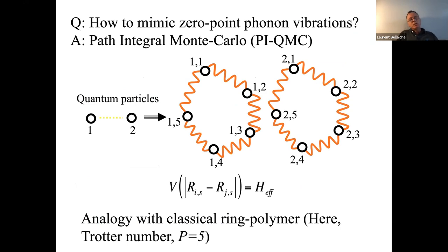Imagine you have interaction between two particles on the quantum level, particle one and particle two. Quantum effects means that particle one self-interacts with itself via a classical ring polymer. And this is denoted as the Trotter number. So if it interacts five times with itself, it means your Trotter number is five. Same thing for particle two, it interacts with itself. And then there are interactions between particle one and particle two at each imaginary time. And this interaction in our case is given by the effective Hamiltonian technique.